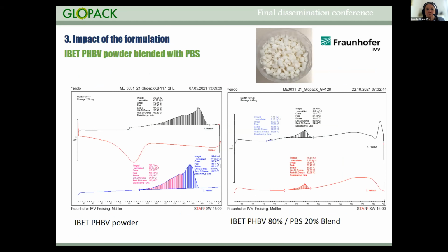We decided to go with 20% of PBS in the mixture with PHBV. You see it in the picture, again white granules. We also hope to improve the flexibility of the material by adding PBS. And in the melting behavior, the impact of the 20% PBS is visible by a lower melting point. It's around 90 or 100 degrees in comparison to the pure material with a melting point around 140, 150 degrees. And therefore we hope also to get a wider processing window.